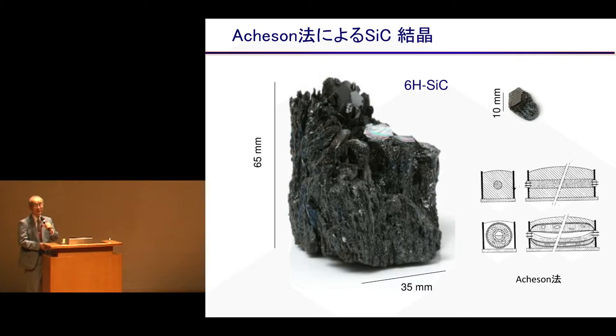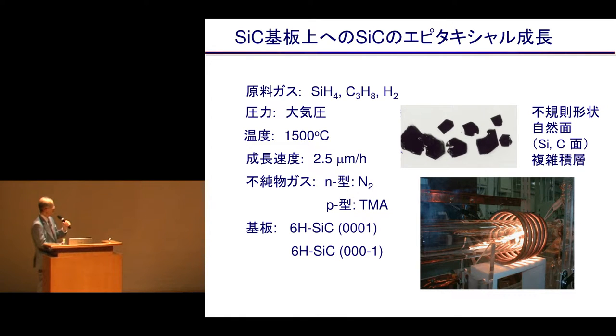And so on the silicon carbide substrate, we had no substrate available in the market at that point. For abrasives or for fire brick, there was an industrial material, the Acheson crystal. So there's a single crystal shown here. And this part was cut off by hammer, and the reverse side was polished, and silicon carbide was to be developed or grown on this surface. It's not silicon, so we could elevate the temperature.